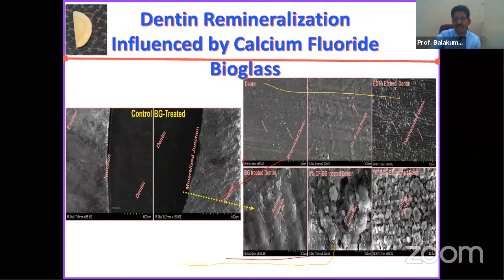We see whether this tooth is growing or remineralization occurs. So the remineralization experiment showed that, for example, this is the enamel structure, and this is a dentin where we attach the bioglass. When we attach the bioglass, after some time, at this junction you can see there is a growth. But the systematic analysis found that your bioglass converted into HCA, that is the natural hydroxyapatite layer, that is demonstrated.